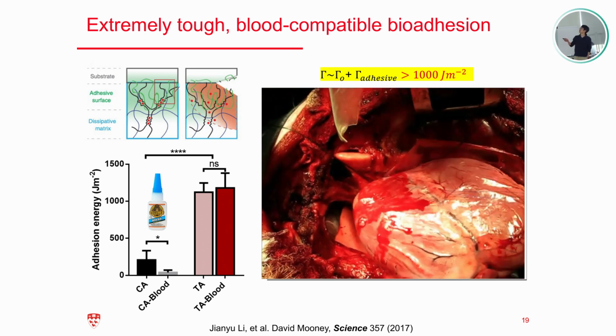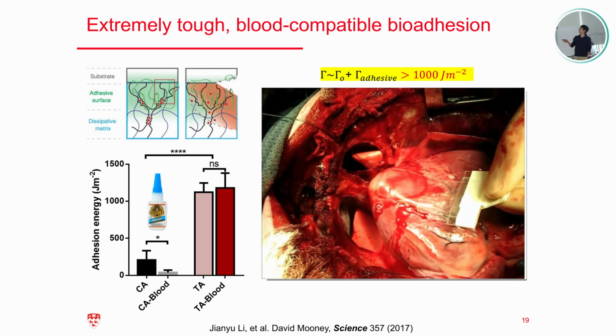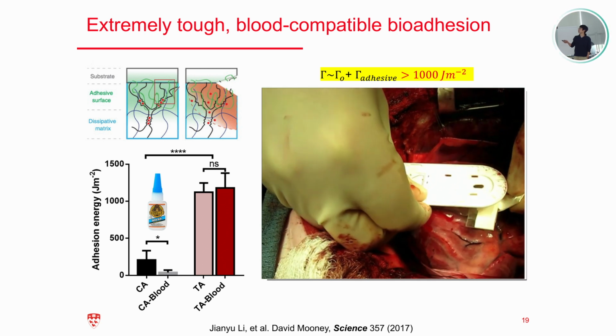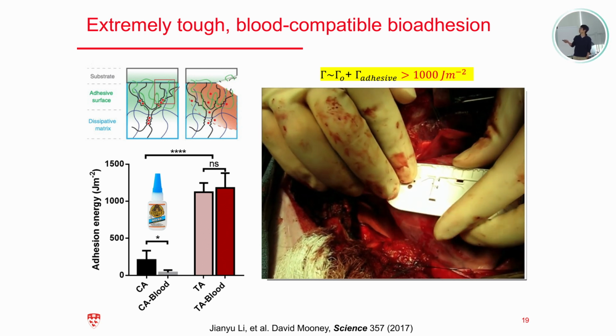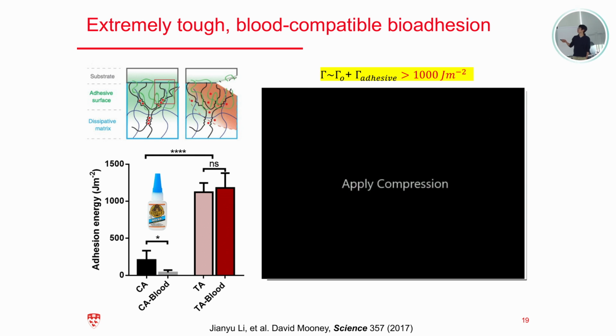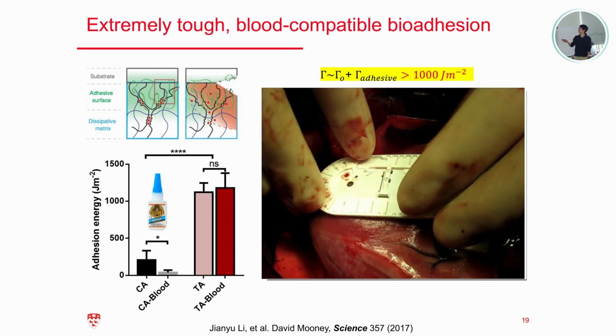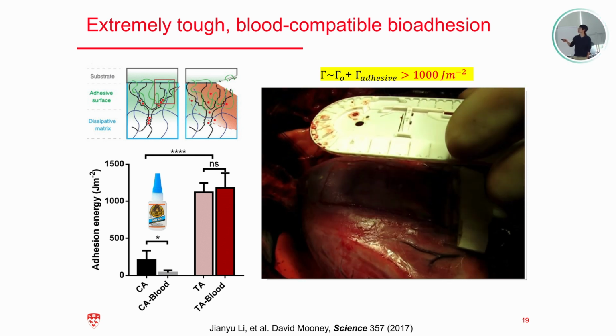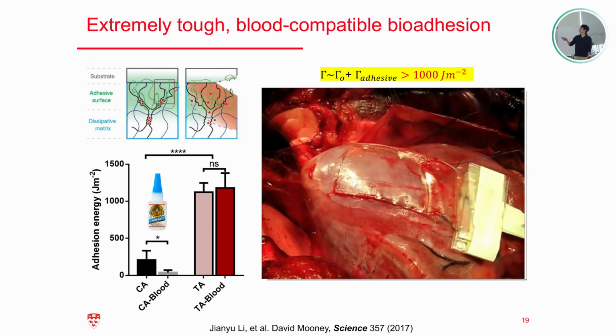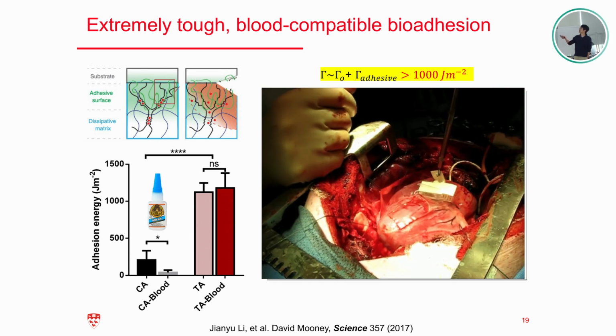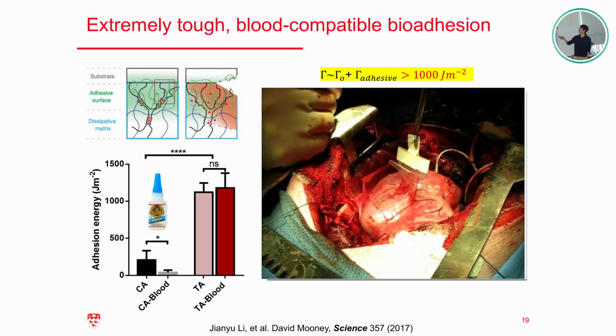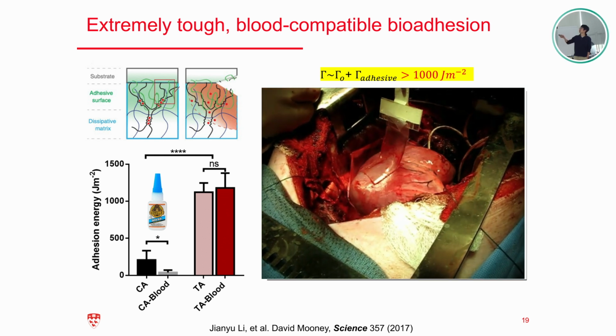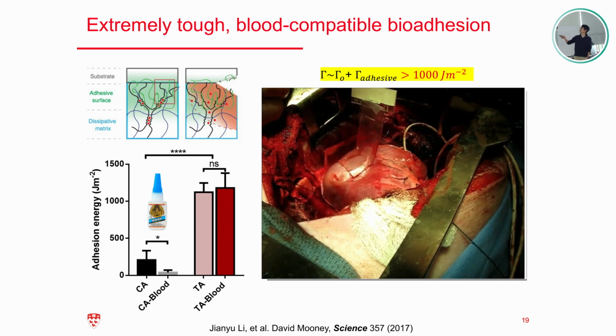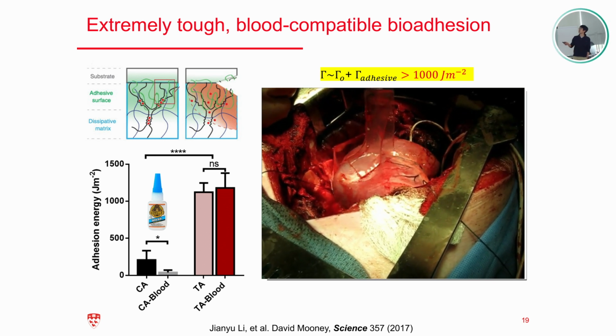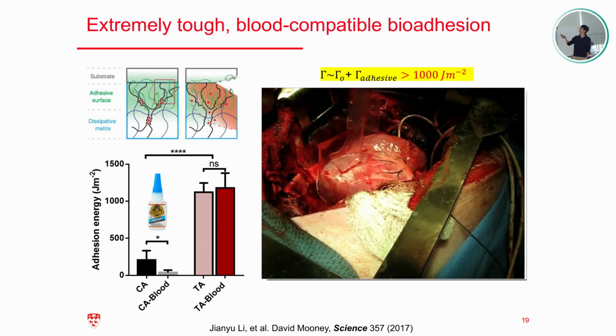application. We apply this bioadhesive on a dynamic, wet, blood-exposed heart surface, and we apply compression in about 2 minutes, and we can form a very strong adhesion in the location of compression. And the surgeon can try to peel this adhesive off. As you can see, as I promised, the matrix is very tough and stretchy, and the adhesion is very strong. Together, we achieve a very high adhesion energy.